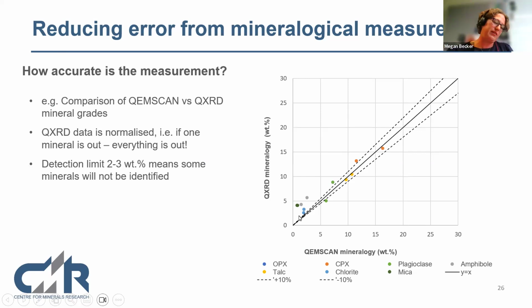One of the issues with XRD, if anyone's worked with it, is that the way we work out quantitative mineral grades, using Rietveld refinement, normalizes it. So everything must add up to 100. If one mineral is out, every mineral is out. I also know that the detection limit is about 2 to 3% for something like XRD. So for anything less than about 5%, I might not get a very accurate number. But if the XRD says it's there and the AutoSEM says it's there, but they're low concentrations and my assays match, then I've got the confidence. So I will use both sets of measurements to give me confidence in the mineralogy data.